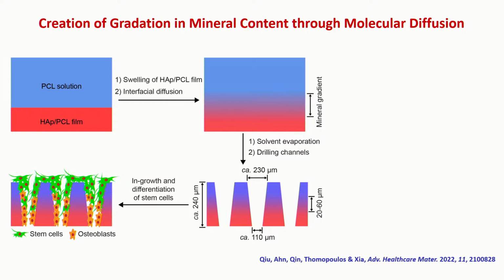You just take the solution of this polymer on this film, you precast on the dish. And then during this aging process, the solvent will be able to penetrate into this PCL composite film underneath. At the same time, the PCL polymer from the bottom can diffuse into this solution phase. So at the interface, eventually you're going to form a gradient in this way through the interdiffusion of hydroxyapatite particles and the polymer chains.